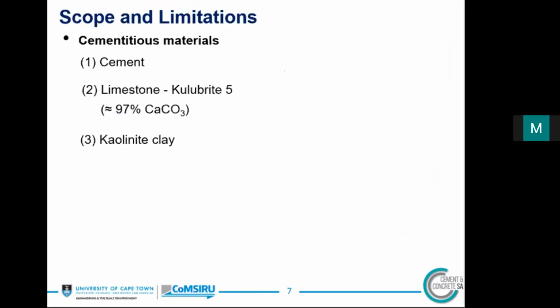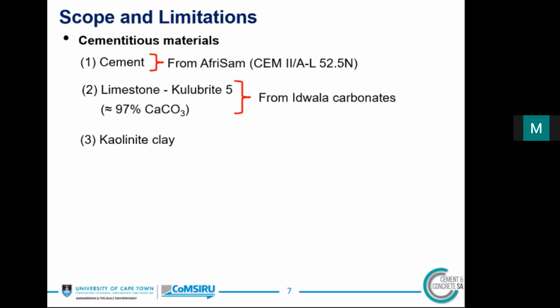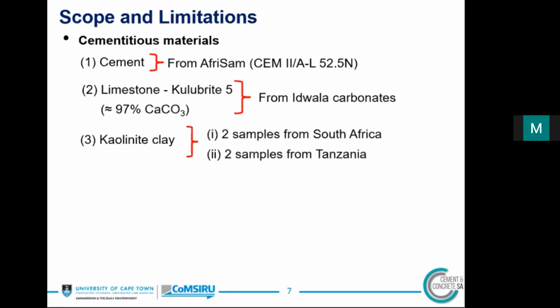Now, the cementitious materials considered in this study are cement, limestone, and kaolinite clay. Cement is CEM II A-L 52.5N from AfriSam. The limestone is Kulubrite 5 from Idwala carbonates, which has about 97% calcium carbonate, and 2 samples of clay from South Africa, 2 samples of kaolinite clay from Tanzania.